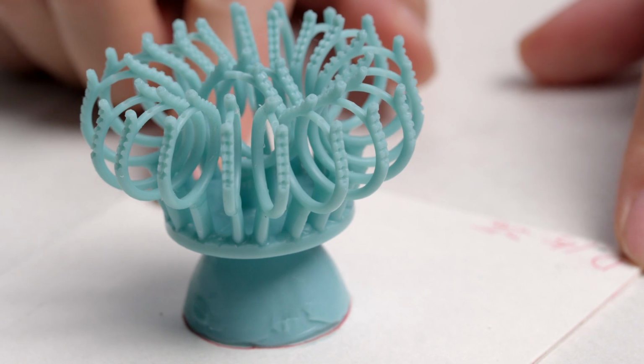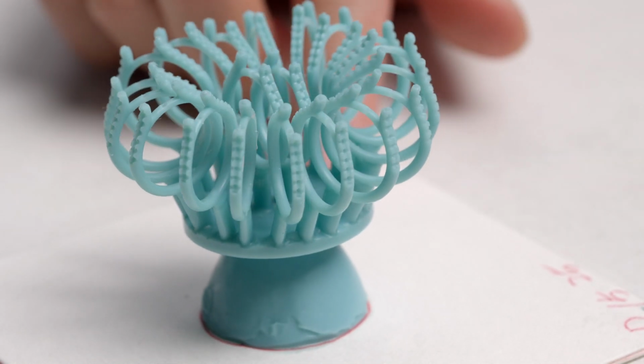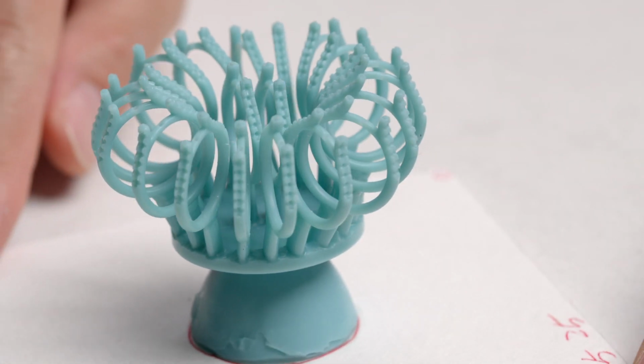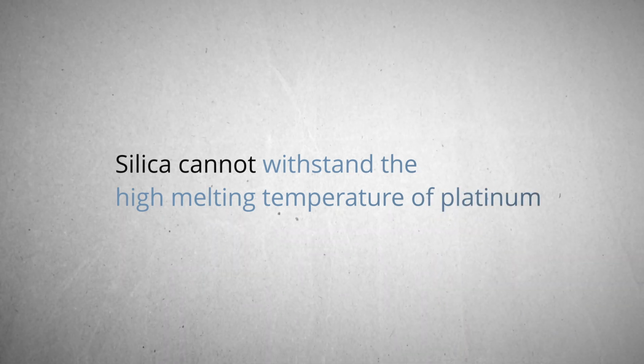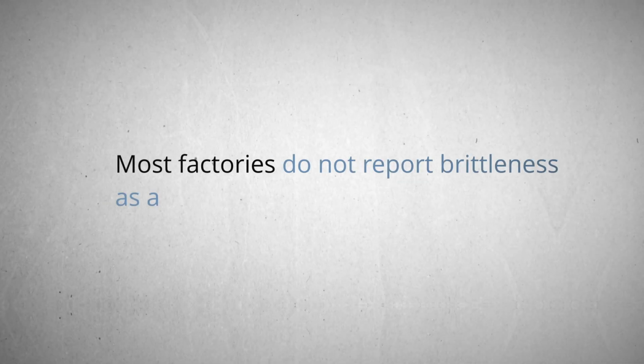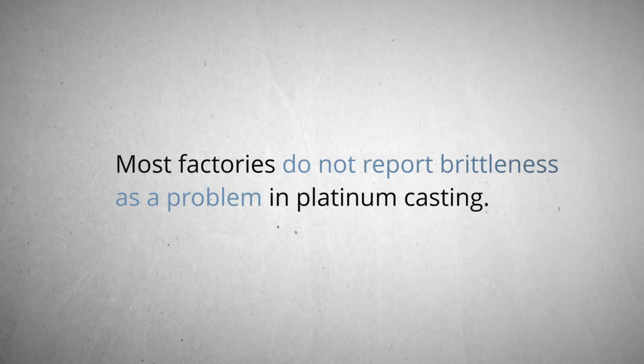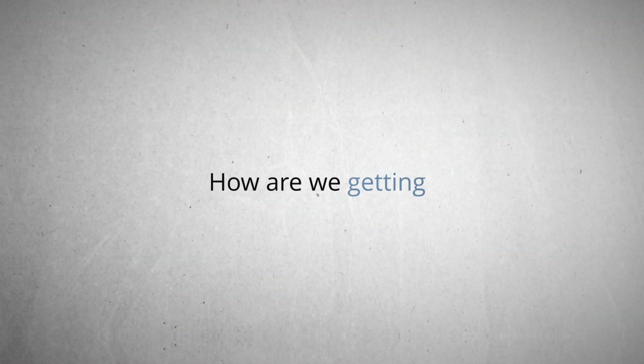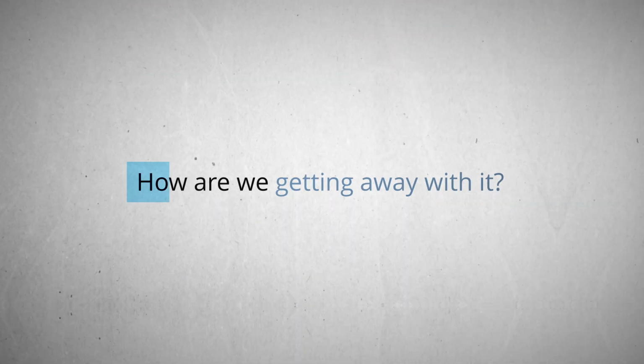And like we said, this is going to cause brittleness to our platinum alloy, and that's something we definitely do not want. So technically, silica ceramic actually cannot withstand the high melting temperature of platinum, at least not for an extended period of time. Most factories actually do not report brittleness as part of the problems with platinum casting, so we can only assume that silicon contamination isn't their top-of-mind problem when it comes to casting. So there must be a way we're getting away with it, but how?